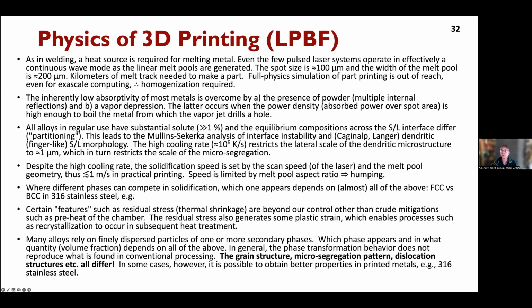So perhaps not all of you are intimately familiar with the basic physics of 3D printing of metals. Many people call this micro welding. In other words, the dominant technology is laser powder bed fusion, which just means you spread a layer of powder, come along with your laser, and wherever you want solid material, you melt it. You do this such that the spot size is typically about 100 microns, and the melt pool that you generate, moving at typically a meter per second, is a couple of 100 microns wide. And that means that for a layer thickness of order, say 40 microns, you need many kilometers of these melt tracks in order to build your part, which means that it's very slow, can take 2 or 3 days to print your part, so that makes it rather expensive.